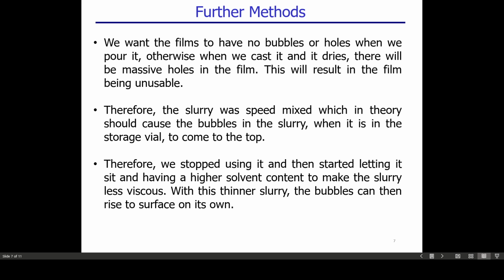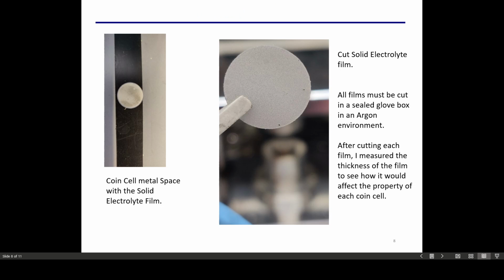Therefore, we stopped using speed mixing and simply let it sit. And while letting it sit, we also let it have a higher solvent content, making the slurry less viscous and thinner. And with this thinner slurry, the bubbles can then rise to the surface on their own, resulting in a slurry that doesn't have bubbles, and when you cast it, it'll have a nice even film. And the result of that can be seen in these two pictures.